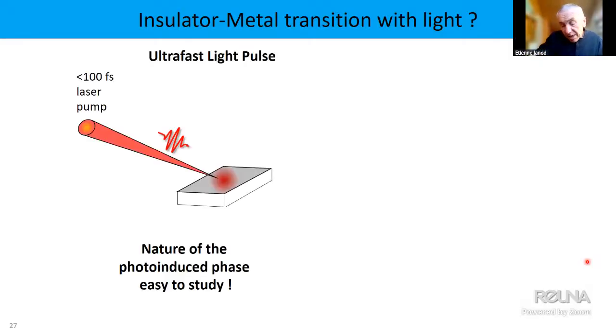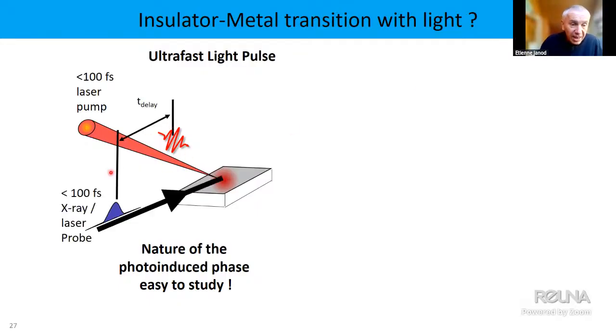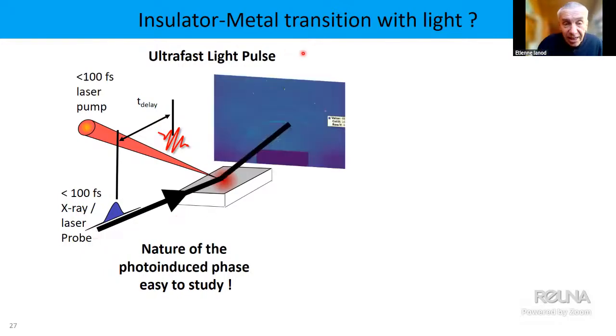And I briefly recall the kind of technique we use to answer this question. We use what we call the pump-probe technique. Usually we have a sample here. We send an ultra-fast laser to the sample, a laser whose duration is lower than 100 femtoseconds. And soon after that, with a controlled delay, we send another pulse that we call the probe. It can be an X-ray pulse, or it can be another light pulse, a laser pulse. Here I give you an example of what happens when we send a laser pulse. For example, we can do diffraction of the material. You see here the Debye ring, the diffraction ring associated with the material.